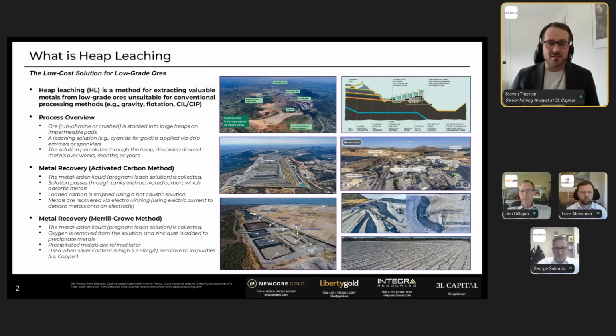The solution is then passed through tanks containing activated carbon, which absorbs the metals, and where the loaded carbon can be stripped later. The metals are then recovered by electrowinning and smelted and poured into gold bars or buttons. Alternatively, the gold and silver could be recovered using the Merrill-Crowe process. This process removes oxygen from the pregnant solution, adds zinc dust, causes the metals to precipitate, and allows them to be refined later. And typically, you'll use a Merrill-Crowe when the silver content of the mineralization is high.